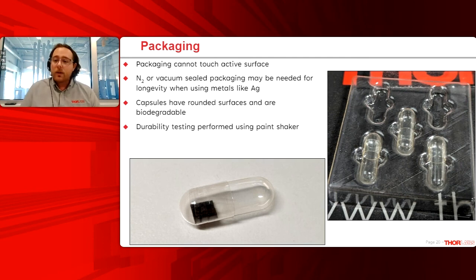The pill capsules are rounded on every single edge, and as an added bonus, they are made of gelatin, so they're biodegradable, which is in line with our sustainability initiatives. So to test this packaging solution, we did a durability test. We placed chips in the capsules and then placed the capsules in a paint shaker. We would then shake the packaging for some time to simulate maybe a bumpy road, maybe someone drops a box somewhere along the line, to see if these chips would perform the same. And through this durability testing, we did find that there was no degradation in performance, even after this vigorous shaking.